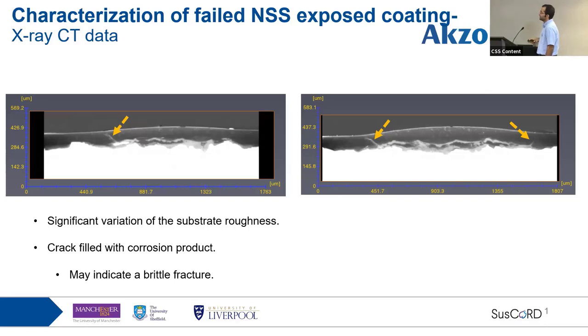First of all, we observed that a crack is forming there. So corrosion starts to form for a reason, and then when the corrosion product volume increases, at some point a crack forms here. And as I said, we developed a hypothesis that these cracks will go around the blister completely, and eventually will lead to the detachment of this blister from the substrate and will exacerbate the situation. And also the way that the cracks have formed may suggest that this is a brittle fracture that is happening, and these powder coatings are behaving as a brittle material may behave.